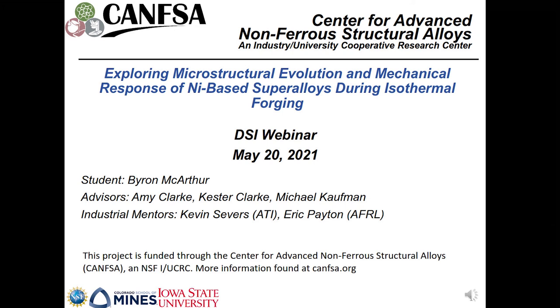I had initially held only at 1 minute to see if that was sufficient. I was having some issues in the Gleeble early on, during that process development stage, before really getting a consistent technique down. But I did go out several minutes of a hold time for those samples to make sure that I had that relatively stagnant or static microstructure prior to deformation.